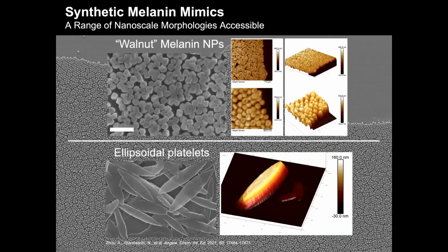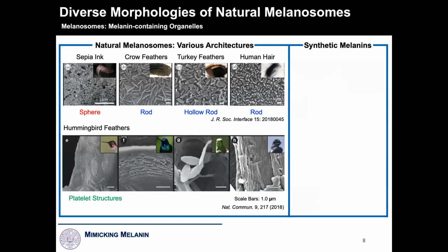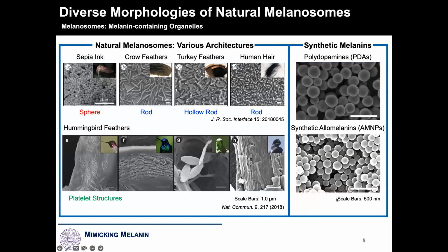This is a very long story to go into all of this, but we can also control their morphology. We've made what my grad students call walnut particles, which have some interesting properties. We've also been able to make platelet type architectures that mimic, as you'll see in a second, more closely some of the melanosomes that are found in bird feathers, including in hummingbirds. So most of the time, synthetic melanins that I'll show you on the right-hand side have been spheres. That's what we're limited to because of surface energy effects. But through some other methods, some templation approaches, we've been able to break symmetry, which is quite difficult to do. And again, get at some of what really is going on in nature.